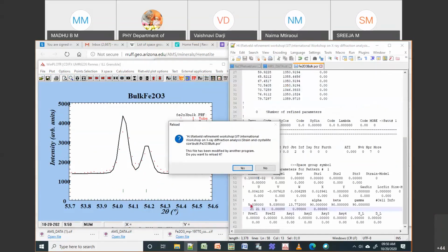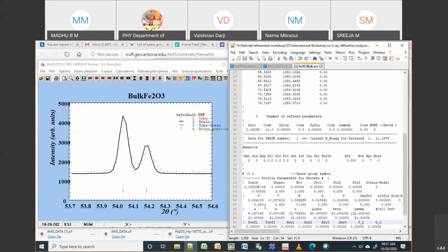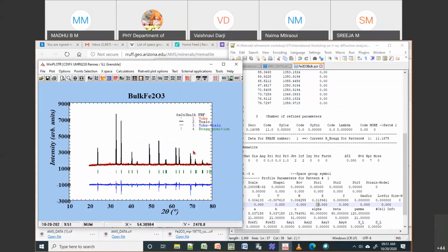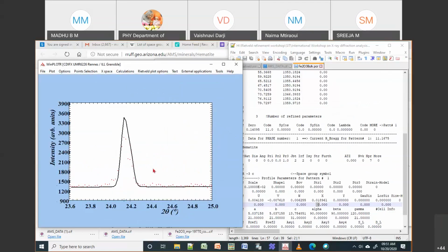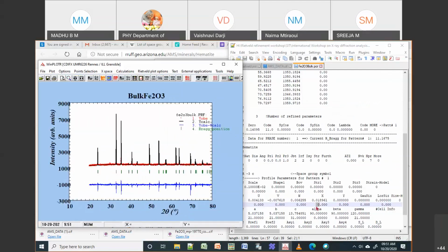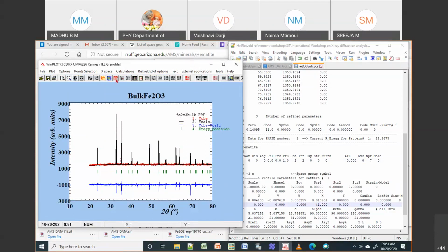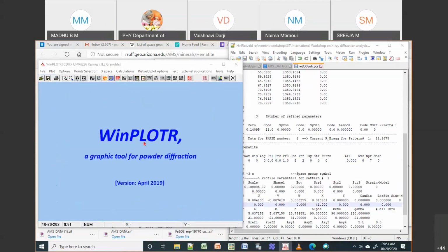So I will go back here. So it was 5.038. So let me see. So it is changed to slightly less. Okay, 5.037, and then it is already a fine fit. I will try to get the peak shape better. Because peak shape is not good, what I will do is refinement for X and Y. Okay, or I'll just do for X, only for X. So I go here. I will ask the program to fit this X. I'll save it. So each time you need to save this. Okay, if not, then it will not take the changes. Okay. So then I'm going to run it again.